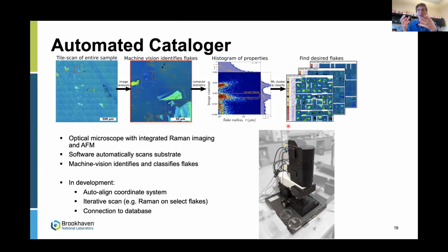In other words, you can classify the flakes and then later treat it as a database where you come in and say, okay, for that sample I just fabricated, show me all the large graphene flakes, all the graphene flakes that are bigger than 1 micron in size or something like that. And then you can extract that information and take a look at it. So this is a faster, more efficient way of finding the good flakes because this can run automated over lunch or overnight. You don't have to sit there and watch it. You can just look at the database at the end and hopefully find the flakes that are relevant to you.